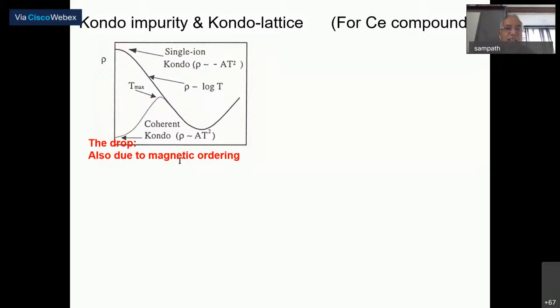Okay, therefore, under the assumption, the story was built for quite a long time, till 2000. I would say that any upturn at low temperature was attributed to the Kondo effect, particularly around 1990 to 94, when an upturn was seen. It was not a logarithmic function. It was essentially a linear function here, and people attributed non-Fermi-liquid behavior, and therefore most of the upturns at low temperature were attributed to non-Fermi-liquid behavior even in Kondo systems, and that created a lot of mess in the literature